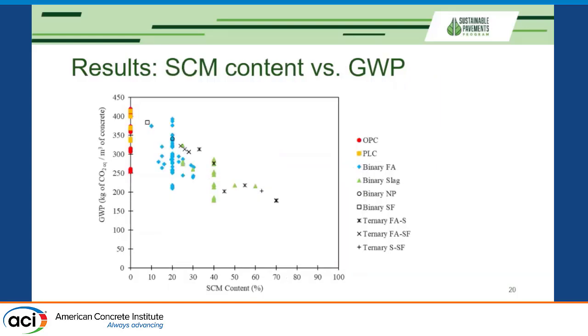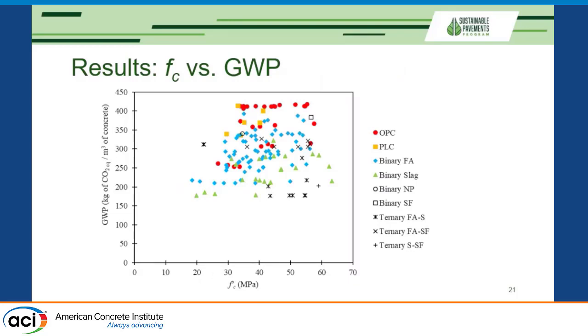And then supplementary cementitious material content over GWP. Here you can see for all of our mixes, we generally have a negative trend, meaning with higher SCM contents, obviously, we have lower GWP.